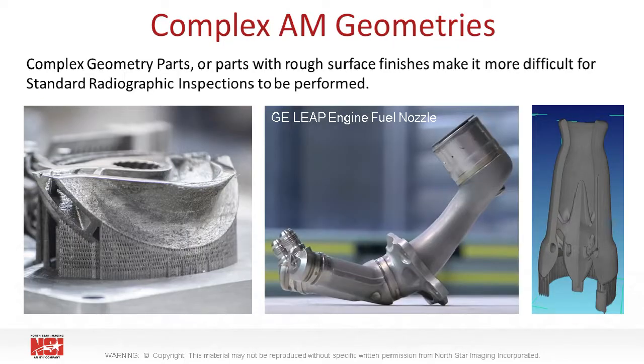Here's just a few examples of parts having complex geometries. One of the cool things about additive manufacturing, of course, is the complexity of the parts that we can make. With that, however, comes more difficulties for the standard radiography methods. When you have multiple superimposed features or rough surfaces, and maybe even combined with lattice structures like the sample on the left, the probability of detection can drop significantly with standard digital radiography, but this is where CT really shines. Also, if you look at performing metrology on these types of parts, measurements of many of the internal features are often not even possible without CT.